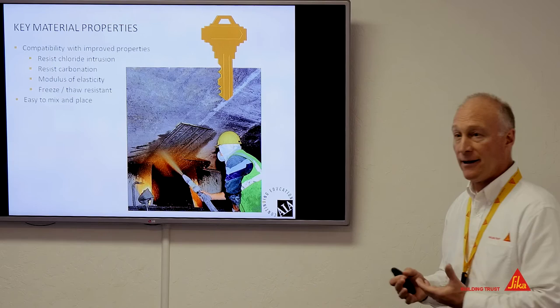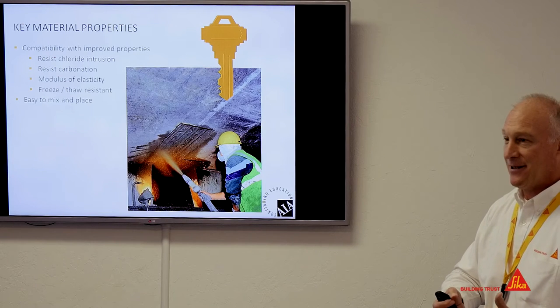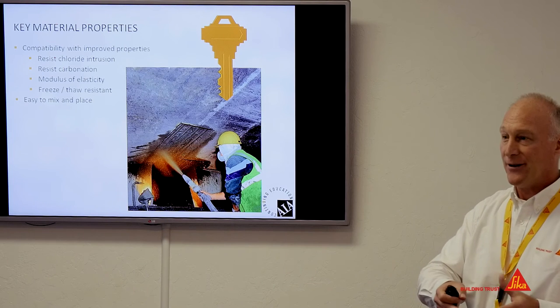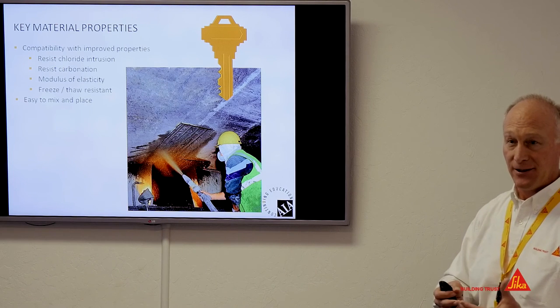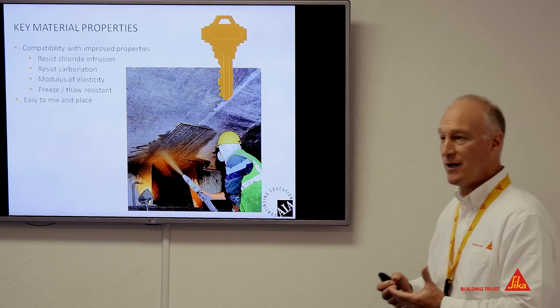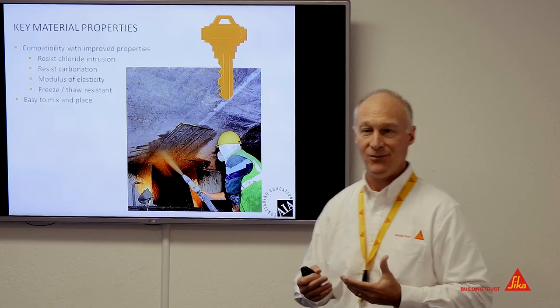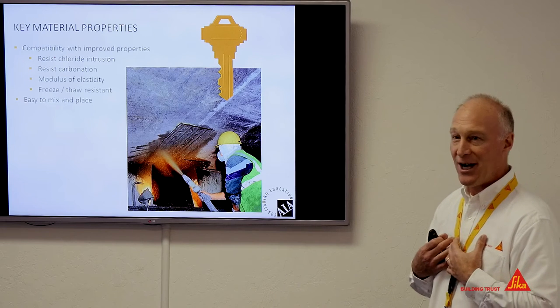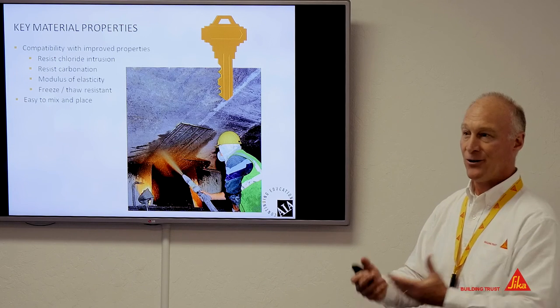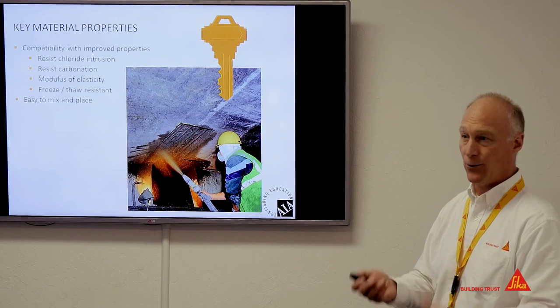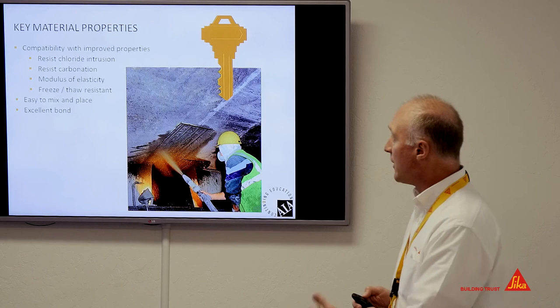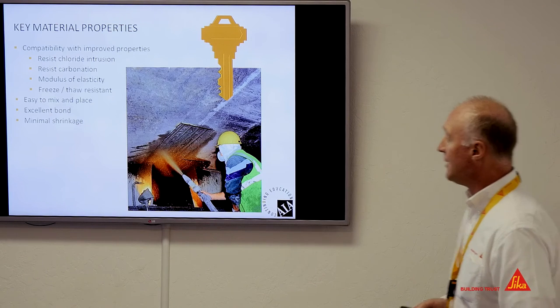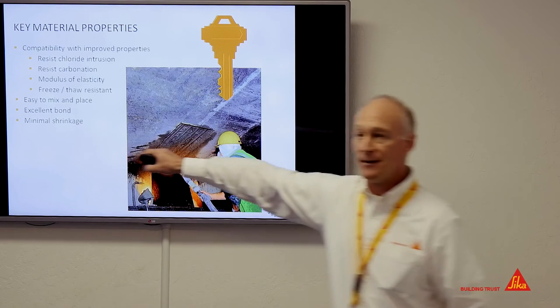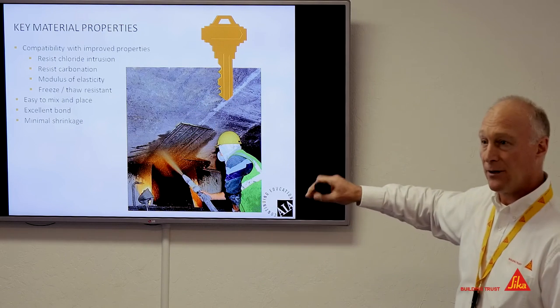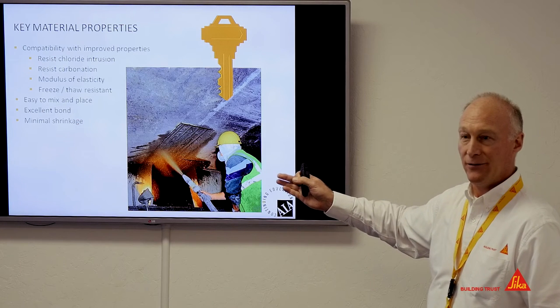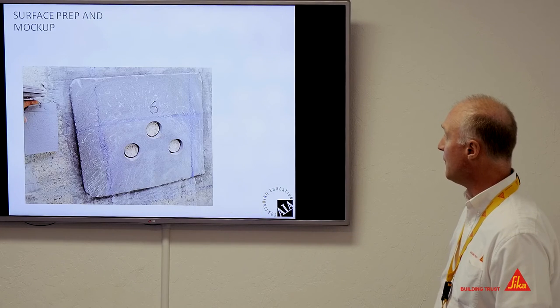But the other thing, I need a contractor to be able to install this, right? So if it works in our lab, that's great, but it needs to work on the site. It needs to be easy to mix in place, because if it isn't, then the contractor may do things to facilitate that, which may not necessarily be desirable. But as a manufacturer, it's our job to make it easy to mix in place so that nobody wants to modify it. They like it the way it is, it's packaged. Then we want to achieve excellent bond and minimal shrinkage. These are the two biggest problems in concrete repair. And if we can deal with bond and shrinkage, minimize cracking, that's 80-90% of the problems. All right, so that's really our main focus.